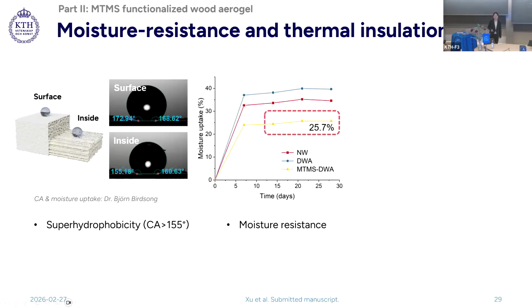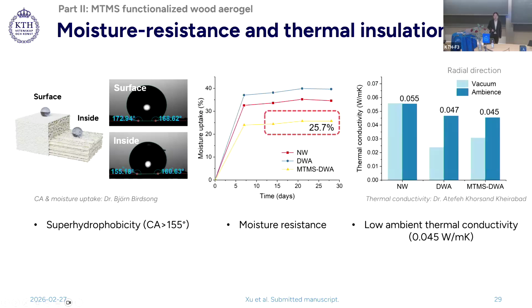MTMS functionalized aerogel also shows improved moisture resistance with moisture uptake of 26% after a 4-week measurement. Moreover, MTMS functionalized aerogel demonstrates improved thermal conductivity under ambient conditions due to its highly mesoporous structure and the reduced moisture sensitivity.